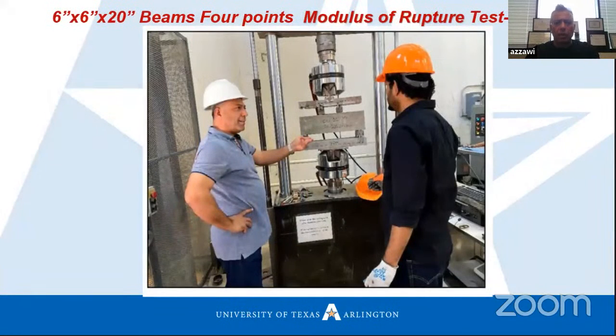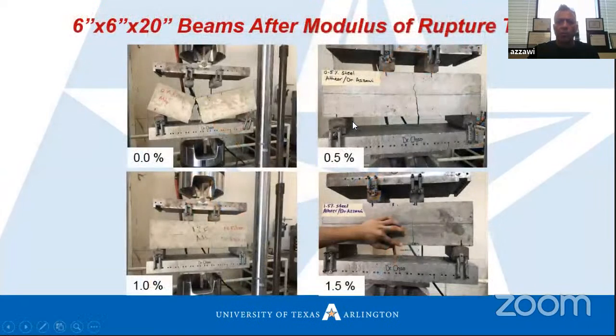This is the flexural test, the modulus of rupture. Also, we have another machine. We apply a 4-point load and find the modulus of rupture for different types of mix. 0% means plain concrete without fibers, then 0.5%, 1% and 1.5% steel ratio. As we see here, we have a brittle crack because we just have plain concrete without fibers. But once we put in fibers, we see some ductile behavior, and we don't have that many cracks.